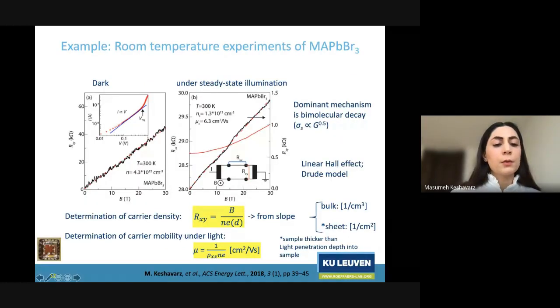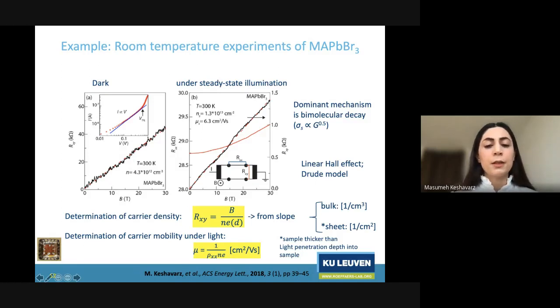Here you see, just again, I repeat that these measurements are done on our methylammonium lead bromide, the orange sample. So we measured a Hall signal in the dark. Before that, to make sure that we are in the ohmic regime, we measure the IV curves, and you can see we apply a current which is in the ohmic regime. The Hall signal is linear, so the Drude model we can use, and from that we can extract the carrier concentration, and from the carrier concentration and the resistivity of the sample, we can extract the mobility.